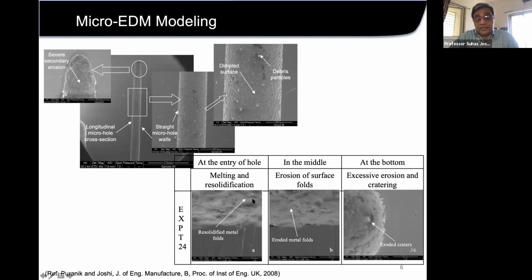You can see that these are the EDM cavities, or craters, which are formed on the surfaces. But in the second part, towards the end or towards the middle, you will find that these surfaces get eroded because the debris particles cannot come out from the process. The hole being very, very small, the debris particle ejection becomes very difficult in that case.